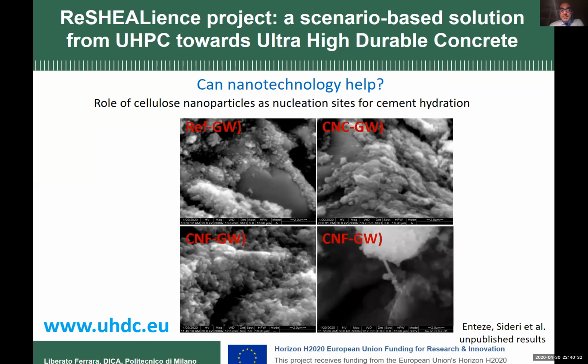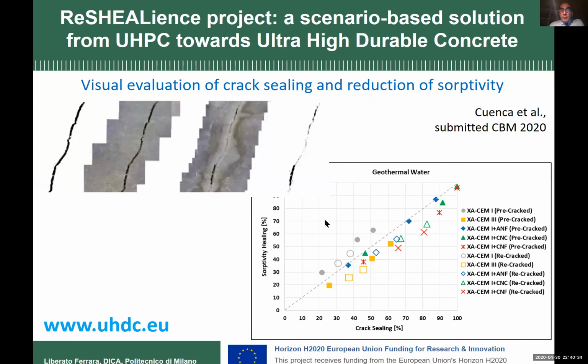We also made an extensive characterization test, and you can see how the healing was improved. In this graph you have the efficiency in recovering the impermeability versus water penetration and the closure of the crack. The gray points are the reference mix, the blue are the alumina, the green and red are the nanocellulose. So the nanoparticles always bring higher efficiency in the self-healing process.